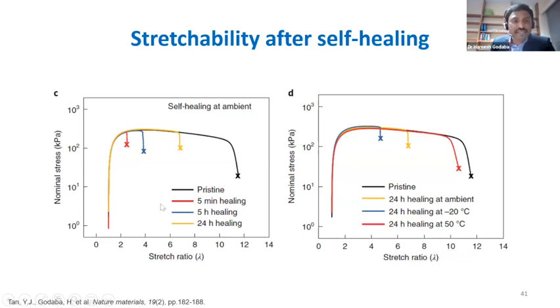And then this is basically how the strength of this material regains. You can see that after 24 hours, it regains about half of its initial stretchability when cut. And if you actually have temperature of 50 degrees Celsius, it can regain close to its initial strength.